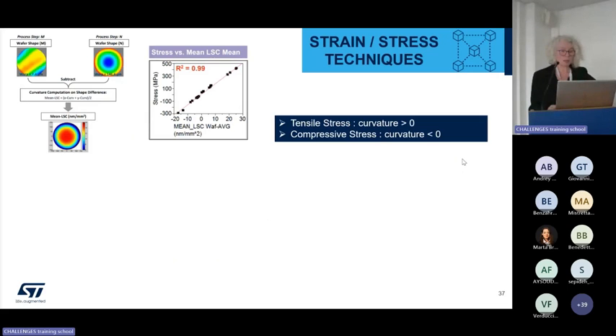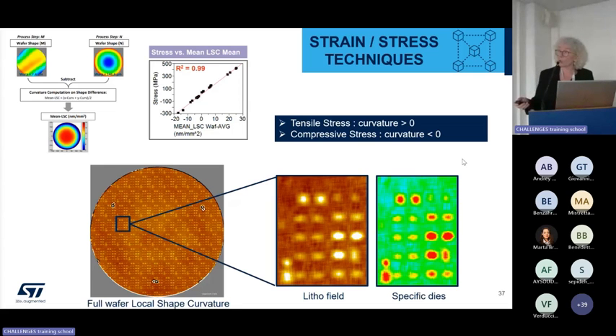Just to finish, we also can have some information about the stress and strain at the wafer level. Here it's before deposition of a film and after deposition. You can do the subtraction and get the information about the influence of the deposition of your film on the deformation of your wafer, but at the local shape curvature this time. And you can have a very nice picture of the wafer, and you know very well what is being stressed, which part at least of the device is being stressed by what and to what dimension, and so on. So this is very nice information about stress and strain.